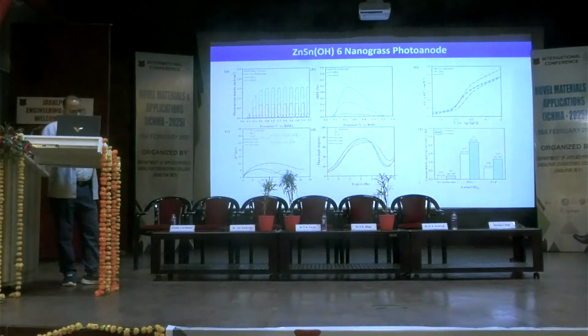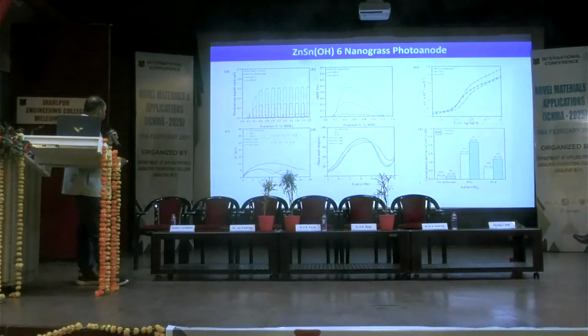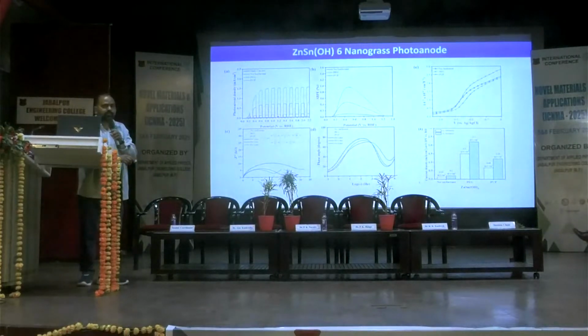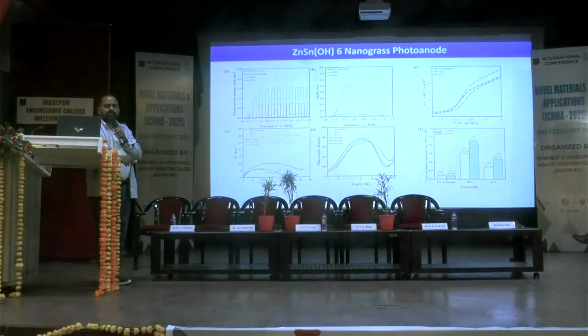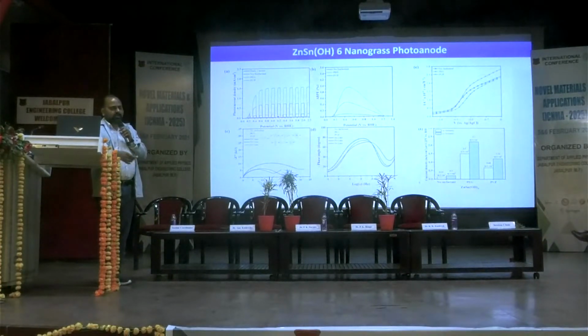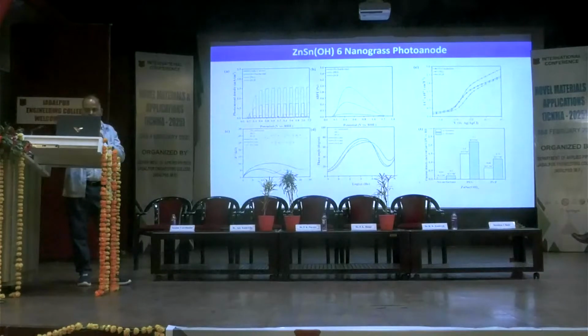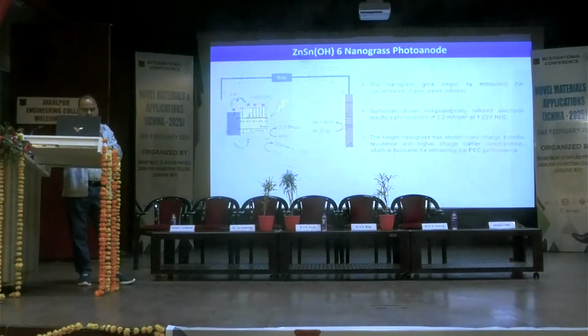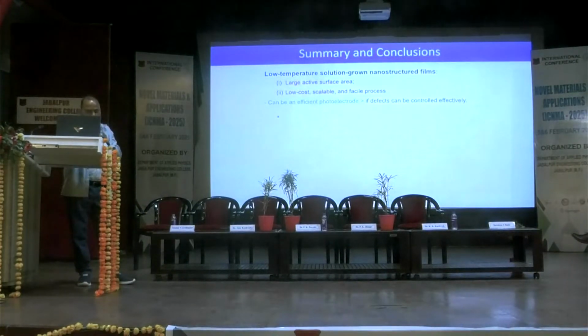And these morphological changes contribute again, and we could get better performance. If you see here, the current is almost 1.5 milliamperes. Now you can ask for the comparison I showed earlier. In other metal oxide systems, the current was less than 1 milliampere, but in these systems we are able to get 1.5 milliamperes per square centimeter, even higher, without any kind of coating or surface modification yet. So we are still planning to modify these systems for further improvement. I think I can summarize here.